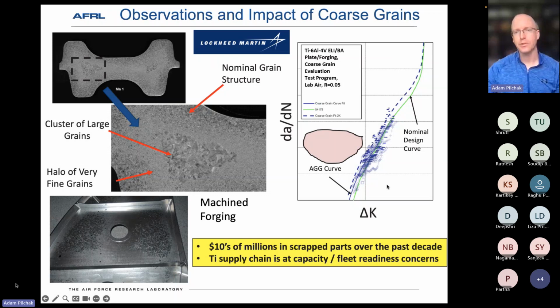If you cut compact tension specimens out and you run conventional fatigue crack growth curves, you find there's maybe a small debit between, say, a typical conforming microstructure and what you might get with the abnormal grain growth. And so that's not too bad. People can live with that, alter inspection intervals. But what this approach doesn't consider is what's known as the small crack effect. And so that's what I've kind of just sketched in this reddish bubble there.